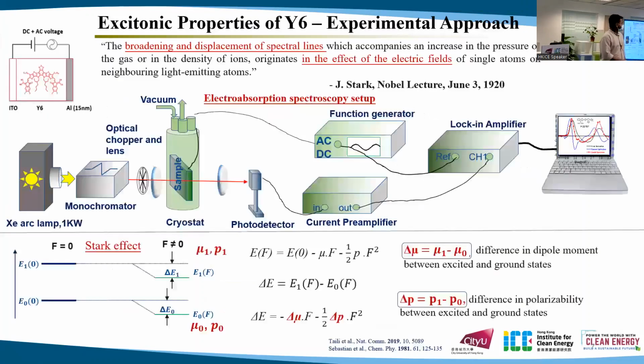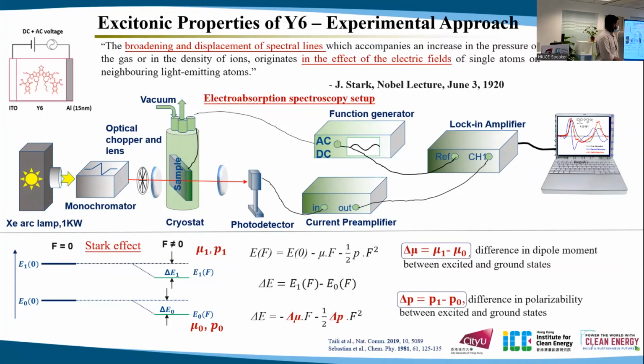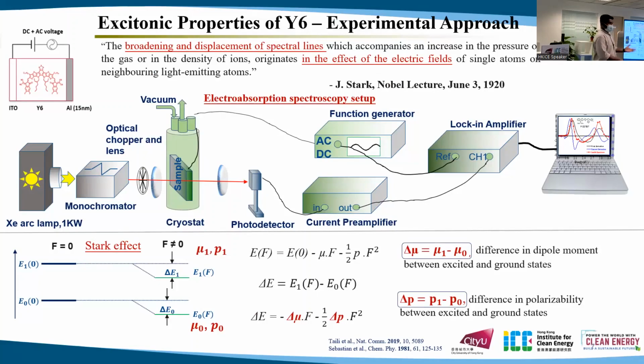spectroscopy. And this is the setup that we are using in our lab. We are using a transmission mode, and the sample is placed in the cryostat under vacuum of around 10 to the power of minus 5 millibar. And we have a silicon photodetector to detect the signal, a current preamplifier to amplify the detected signal by adjusting the gain and sensitivity, and a lock-in amplifier to analyze the signal. And we are applying a voltage to the sample using a function generator.